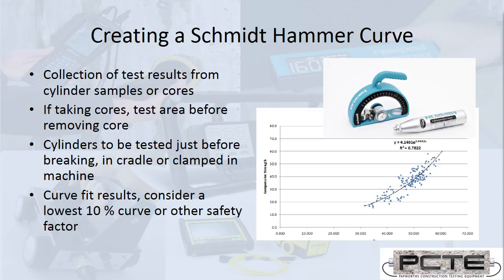Finally, the relationships from a Schmidt hammer do have an inherent uncertainty. When we're striking the surface, there may be a surface inconsistency, or there may be some local variation in strengths over that surface area being tested. So we do want some form of safety factor. One useful way to do that is to use a lowest 10th percentile curve. The principle there is, if you look at my curve on the right, we have a line which represents the midpoint of those test results. If instead we map out a line that places most of our test results above the curve, we're going to have a more conservative strength relationship when we use that curve. Finally, once you've got this graph, we can read up from rebound results to get compressive strength results.